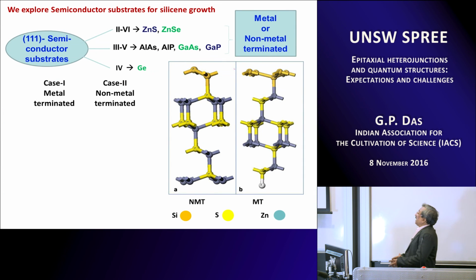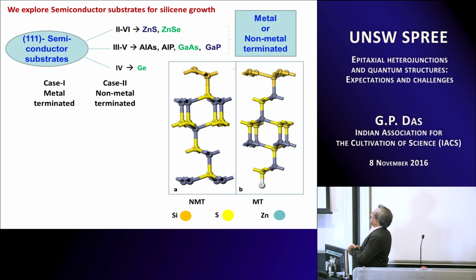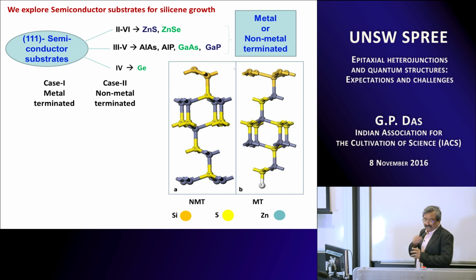Now, as I told you that we tried semiconducting substrates to grow silicene. So when you try to grow silicene on either II-VI or III-V substrates, then you have to remember one thing. Is the silicon of the silicene getting bonded to the metal or to the non-metal? So it can get bonded to zinc or it can get bonded to sulfur.